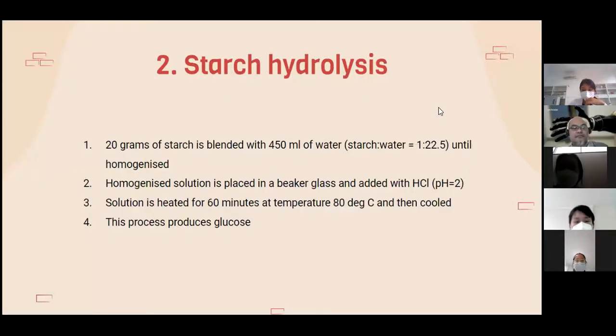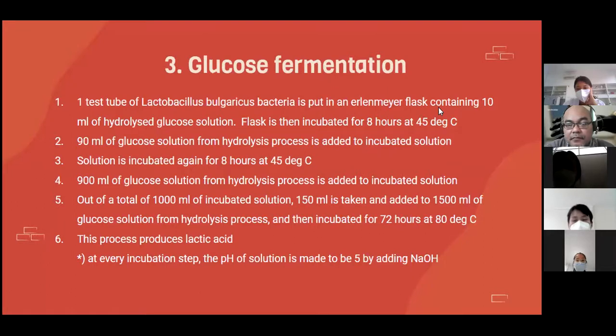Next, after the isolation, the starch will be hydrolyzed. So 20 grams of starch will be blended with 450 milliliters of water. The ratio of starch to water always has to be 1 to 22.5 until it is homogenized. The homogenized solution is then placed in a beaker glass and added with HCl with pH 2, and then the solution is heated for 60 minutes at a temperature of 80 degrees Celsius and then cooled. This process produces glucose.